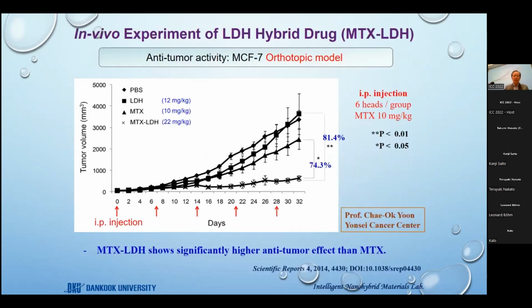So to compare the therapeutic efficacy of MTX and our clay drug, we performed the tumor growth inhibition test in the orthotopic breast cancer model. The tumor volume was measured after intraperitoneal injection of the control solution, PBS, drug carrier only, drug only, and our clay drug into tumor-bearing mice. As you can see here clearly, the MTX anionic clay group showed an even stronger anti-tumor effect than the intact MTX, with a mean tumor volume of 600 cubic millimeters, representing approximately 81% and 74% reduction in tumor volume compared with the PBS control group and the MTX group, as you can see here.